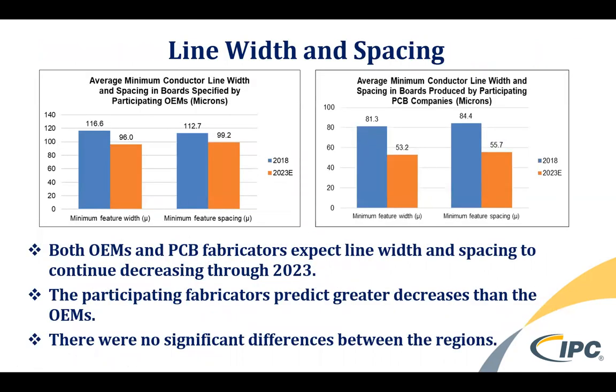As we said, density is also increasing. Finer line widths and spaces, which again drives not just imaging technology and some of the wet chemistry such as develop, etch, and strip, but it's also causing us to look at newer and improved ways of imaging the boards. More and more fabricators are moving away from conventional light sources and moving into LDI, laser direct imaging, and also the improvements that are allowing us to move up the technology curve as well. So line widths and spaces are definitely decreasing. Obviously, what you see here, moving forward, feature spacing is definitely decreasing, as are the line widths and spaces. So we're looking at this as another way of increasing wiring density. But again, that puts a significant strain on the processing people, the fabricators who are trying to build and hold these fine line widths and spaces.